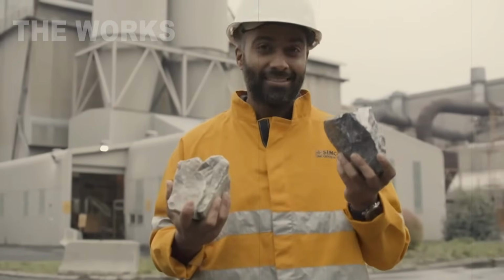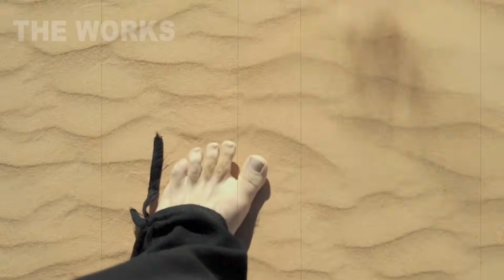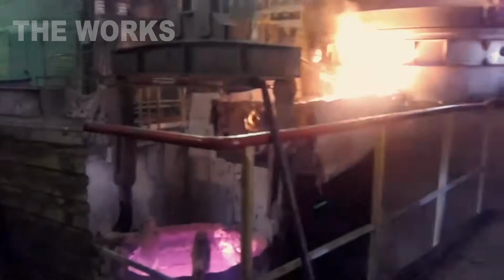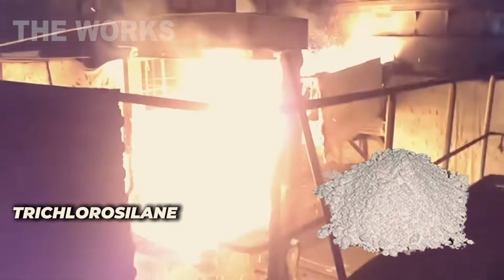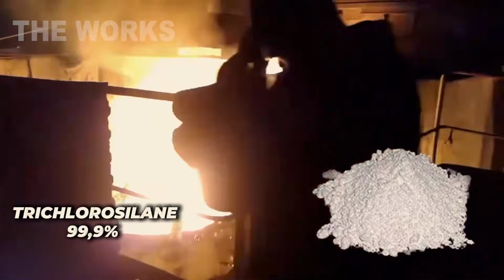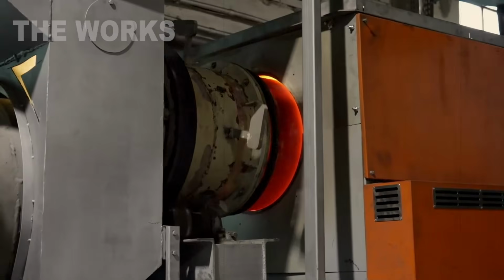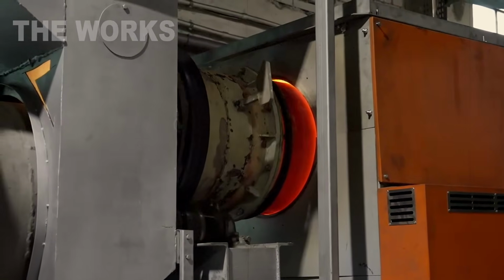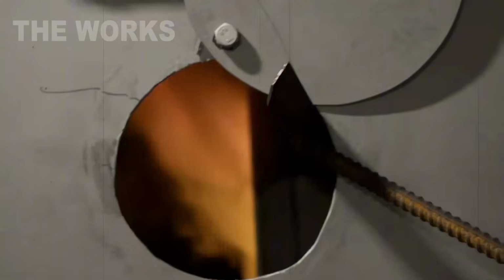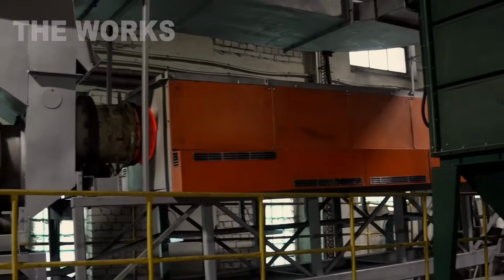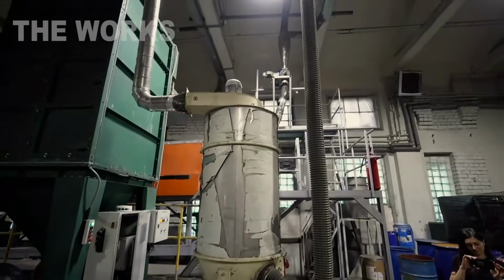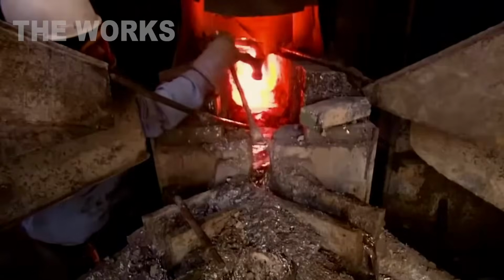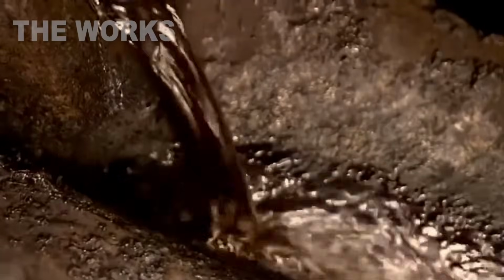After 100 cycles, you get trichlorosilane that's 99.9% pure. Now you need to turn it back into pure silicon. That's where the Siemens process comes in, one of the most beautiful and complex in metallurgy. Inside a sealed reactor, they install thin silicon seed rods. Purified trichlorosilane is fed in along with hydrogen and heated to 2000 degrees Fahrenheit. At that temperature, the trichlorosilane breaks down and pure silicon deposits onto the seeds, building them up layer by layer, atom by atom. The process runs for several days.